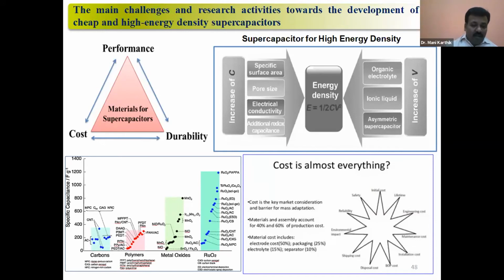You can see on the left-hand side, the people are focusing, as I said, on carbons, polymers, and metal oxides. These are the major materials focused on, and they get very good results. You can see the ruthenium oxide giving 1200 farads per gram. It's very high with different chemistry, ruthenium oxide with carbonate, CNT, or polymers to increase that performance. But even though ruthenium oxide gives very high performance, the cost is very high and the durability is very low compared to carbon. For carbon-based chemistry, activated carbon, the maximum capacitance in organic-based is 100 to 150, but aqueous-based gives 200 to 300.